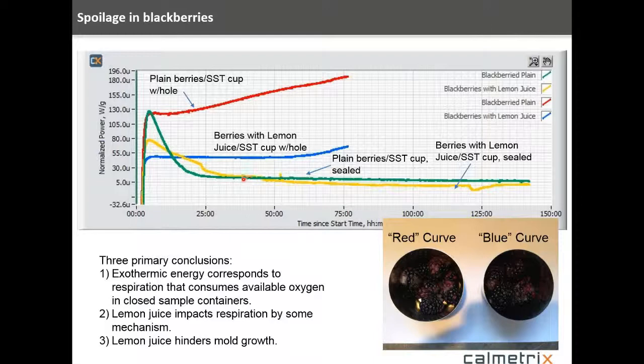It's interesting to note that if you integrate under this curve, you'll see that this relates to the 400 joules of energy that the oxygen consumed in the respiration process. And then all the oxygen was used up and the activity fell off. In the yellow curve, it was treated with lemon juice. Again, the total area under the curve is still related to the 400 joules of energy. However, there were differences in the two curves in terms of that respiration process.